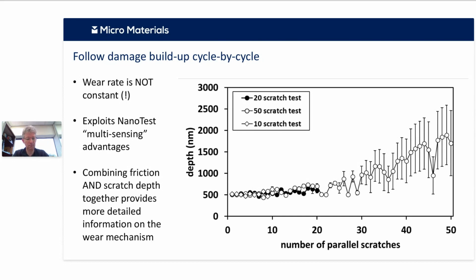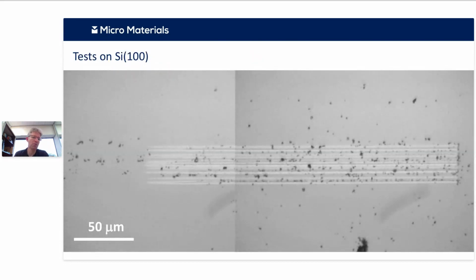So this is the sort of thing that you might get under relatively light conditions. So here's an example on just a silicon wafer, so quite light load, and you're getting a little bit of brittle damage. Those dark spots that are there, but essentially it's quite a fairly well behaved surface.